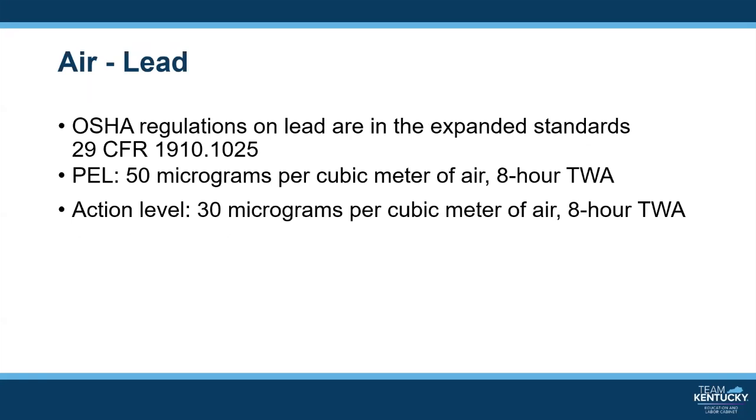Lead regulations are found in OSHA's expanded standards under 29 CFR 1910.1025. The PEL for lead is 50 micrograms per cubic meter of air over an 8-hour time-weighted average. The action level for lead is 30 micrograms per cubic meter of air.